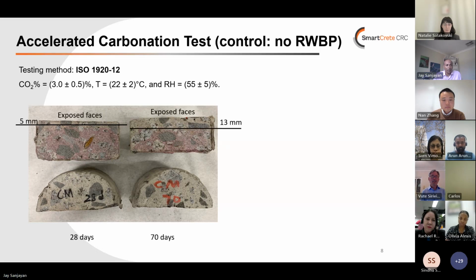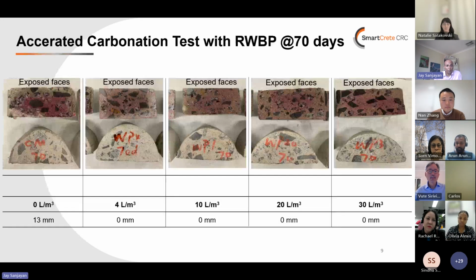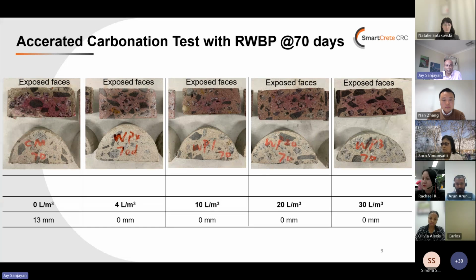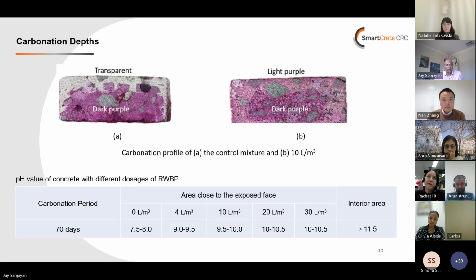And after 70 days, we get 13 millimeters. So that's equal to maybe 20 years of carbonation. But when we did the same with RWBP after 70 days, the carbonation effectively didn't happen. You can see with the 4 liters, 10 liters, 20 liters, 30 liters, the depth of carbonation was, we could not detect anything.